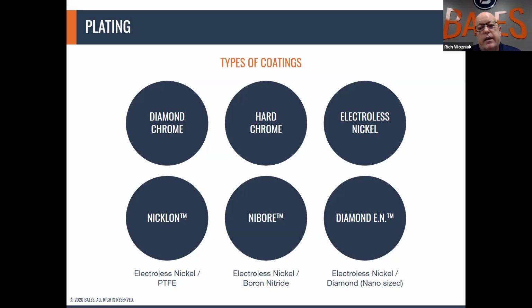Our diamond EN is electroless nickel with nano-sized flakes of diamond. We have an option where you could bring that abrasion protection to a Rockwell surface hardness of 70, which is now almost as good as hard chrome. But what's nice about the diamond EN is it flows evenly everywhere, whereas with hard chrome you have to build a conforming anode, and those things can be a little tricky, especially in a deep pocket where it may be missed. And of course, in this industry, the area that's not protected is the one that's going to wear the fastest, and that's where you'll start to see your issues reappear most of the time.